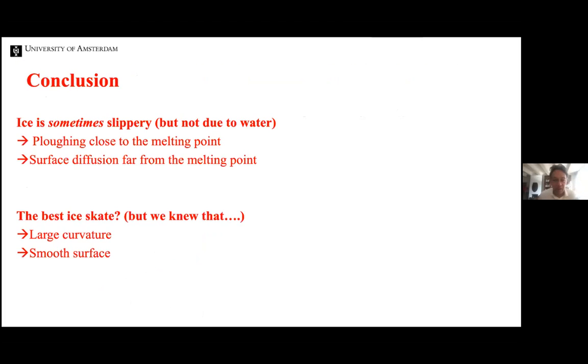Okay, I'm at the end. So if I have to conclude something, I would say that ice is sometimes slippery. At very low temperatures, it's impossible to skate, and if your skates are too rough, it's also impossible to skate. But the two dominant mechanisms are plowing through the ice close to the melting point, which we understand quantitatively, and surface diffusion far from the melting point, which we understand semi-quantitatively. It's still not possible to relate the diffusion coefficient of these mobile molecules to the friction coefficient directly, but the correlation is clearly there.